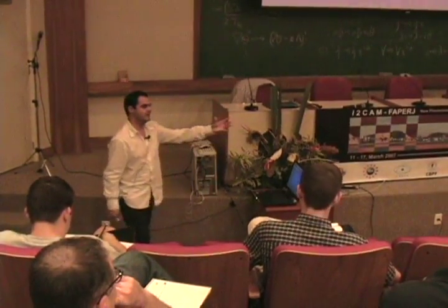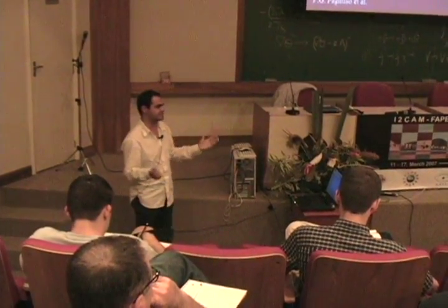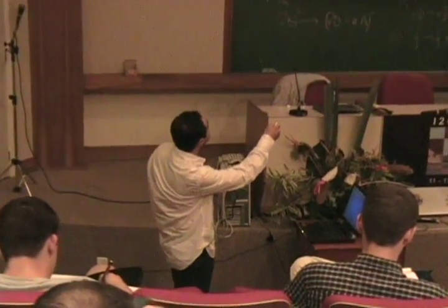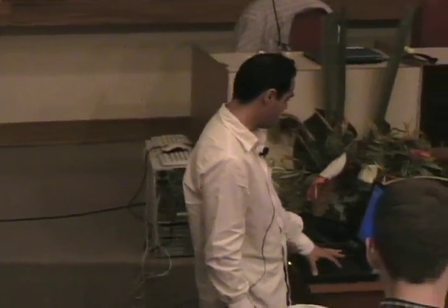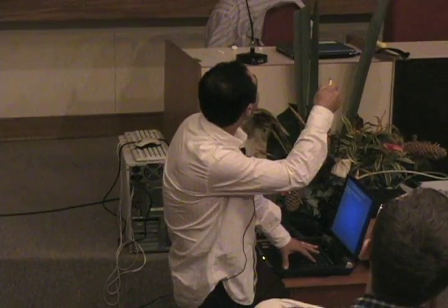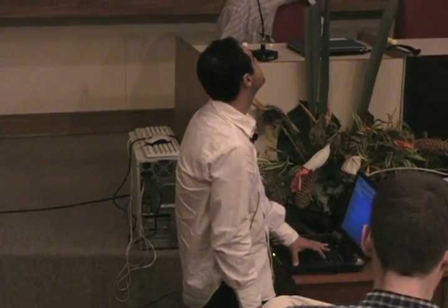If I try to look at cerium, I cannot see it, and that's understandable. If I put gadolinium in cerium rhodium indium 5, cerium cobalt indium 5, no sign of gadolinium. Erbium, neodymium, whatever, I cannot see electron spin resonance, unfortunately, in this system. That's very curious. Even when I try transition metals on the rhodium, cobalt, or iridium side, I cannot see resonance. Not even for the lanthanum analogs.